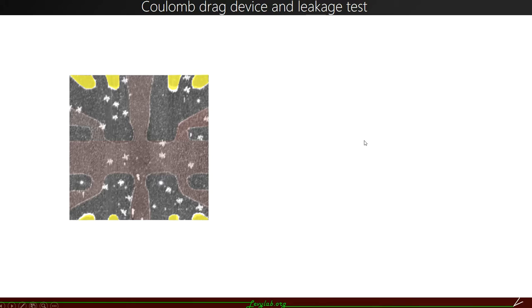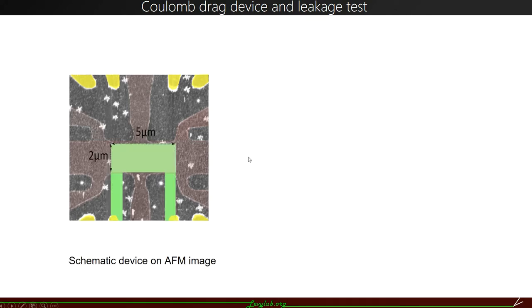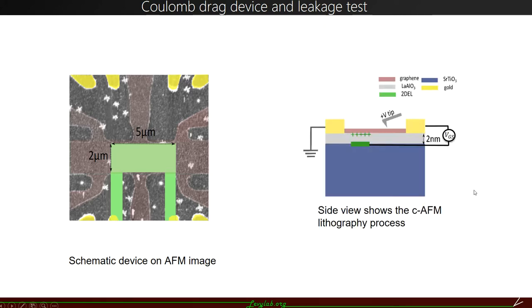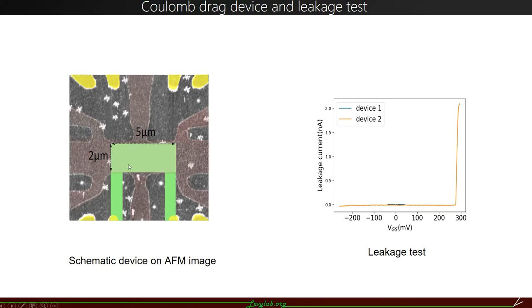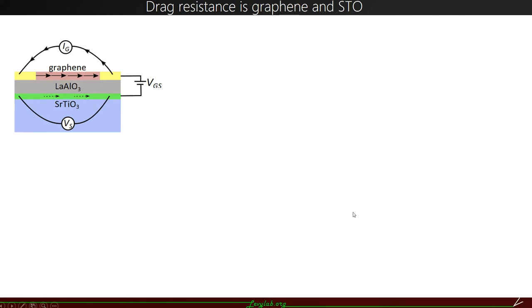With this writing technique, we started to fabricate our Coulomb drag devices. So here is a graphene Hall bar structure, and then we apply positive voltage to the AFM tip and write a conducting region underneath the graphene, and then we connect this rectangular region to the STO interface electrodes to make contact, and then we measure the leakage between the graphene and this green conducting region. As we can see, if we keep the voltage between graphene and STO smaller than 200 millivolts, the leakage current is very small. So we can perform the Coulomb drag experiment between graphene and LAO-STO.